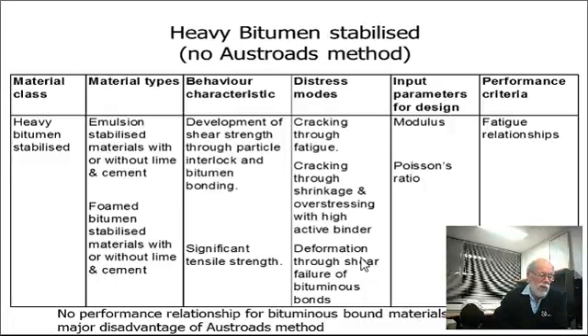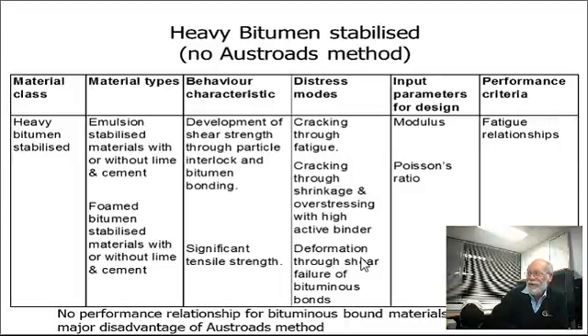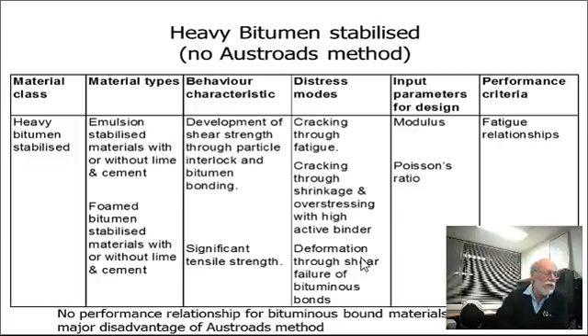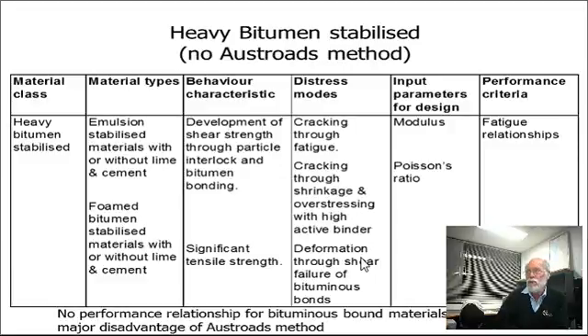So if you don't want any cracking with foam bitumen, keep your lime percentages or cement content low. We used to use quicklime, but the trouble is in metropolitan areas it's a pretty nasty material — it's caustic, dangerous. So we've actually changed over to cement because it's a safer material to work with.